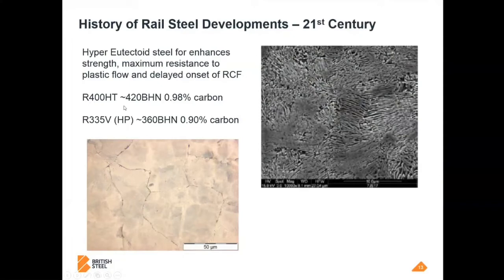It's a nearly 1% carbon rail steel, quite a lot of manganese, a tiny bit of chrome, and it's aggressively heat treated. And they yield a typical 420 Brinell hardness. This is a super premium rail grade targeted specifically at very heavy haul railway lines, like in Brazil, where they're moving the iron ore about. Just heavy freight trains with maybe 35 to 40 ton axle weight, double the UK mainline capacity, incredibly demanding areas to operate a railway. And these super premium grades are targeted at that.